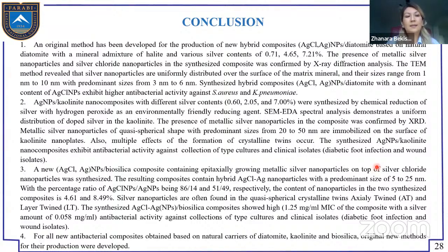efficiency. And second, the kaolinite nanoparticle composite with metallic silver nanoparticles was synthesized with 3 concentrations, and the physicochemical properties were studied, with the formation of metallic silver with size from 20 to 50 nanometers confirmed by X-ray diffraction. And the synthesized composite showed antibactericidal efficiency against 6 strains, diabetic foot infection and wound isolates.